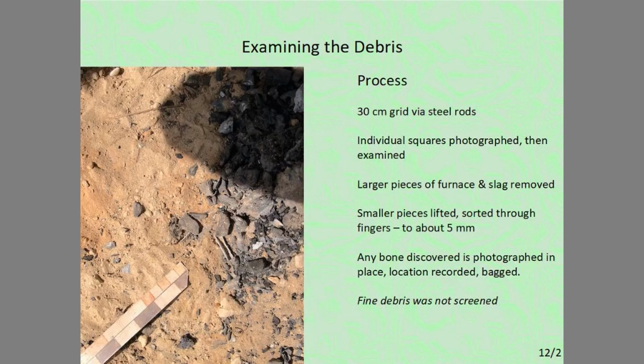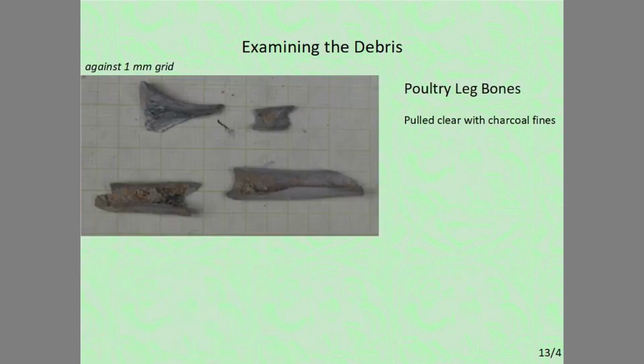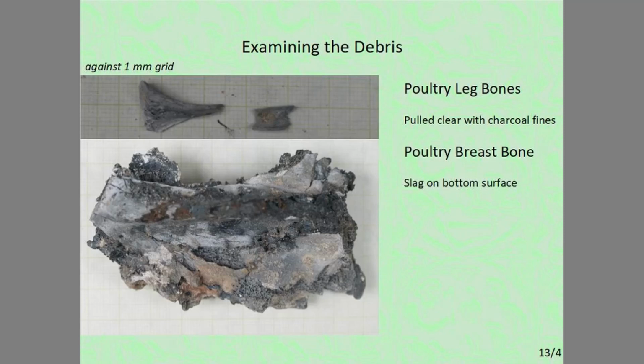As individual fragments of bone were discovered, if possible they were photographed in place, their location was plotted against the overall grid, and then the individual bones were bagged. It should be noted that there was no attempt made to screen the debris beyond the 5mm hand sorting. What was recovered? First, there was a number of small fragments, quite shattered, of poultry leg bones. These were pulled clear with the charcoal fines. There was only one piece of poultry breastbone recovered. It was found with slag encasing its lower surface.